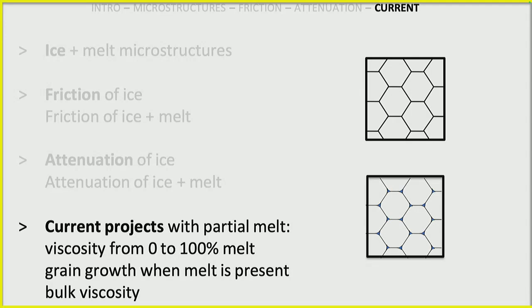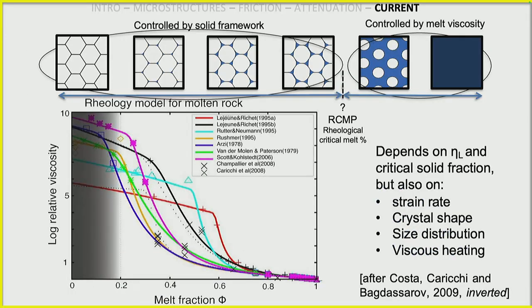I just want to highlight some of the current projects that are happening in the lab. In particular, this is a pretty exciting thing. I've had calls before where people say, Christine, what's the viscosity of ice at melting temperature? It's a range of 16 orders of magnitude, right? Because it's got to pass through this whole range. Pure ice all the way down to a pure water where it's 10 to the minus 3 Pascal seconds versus 10 to the 13.